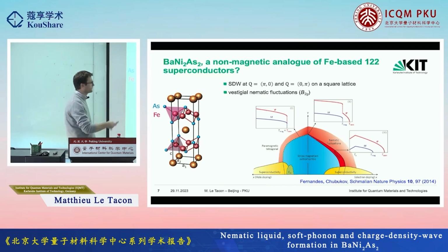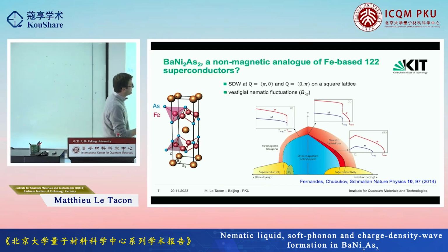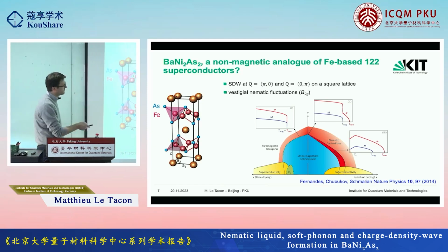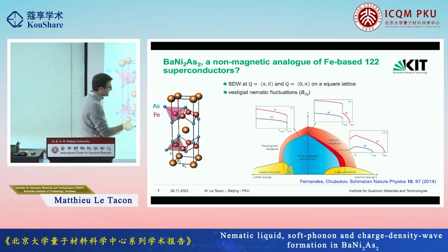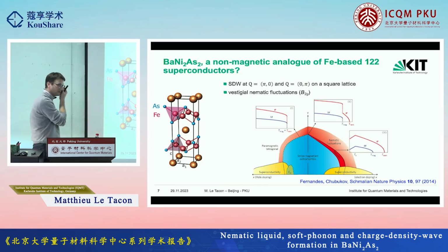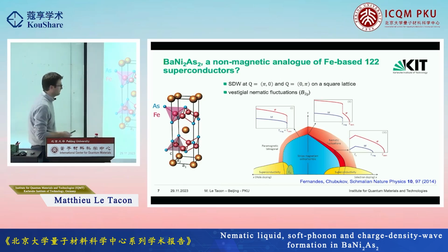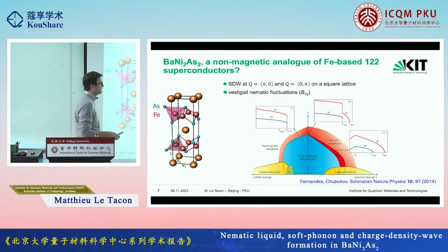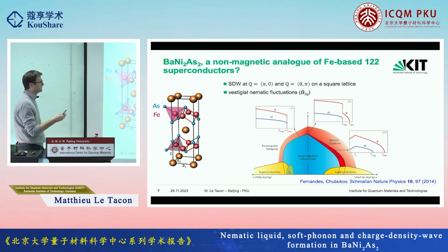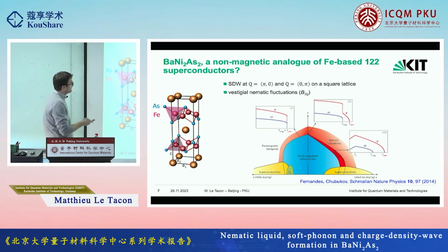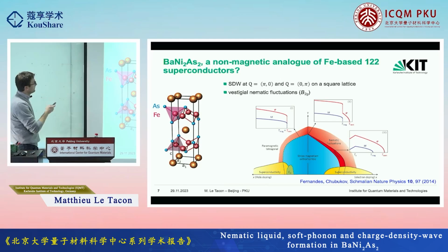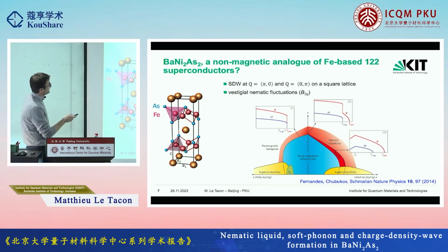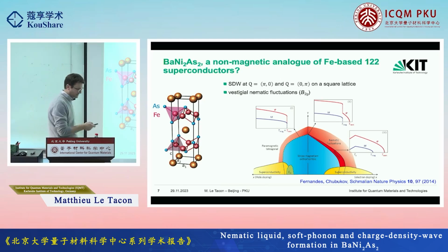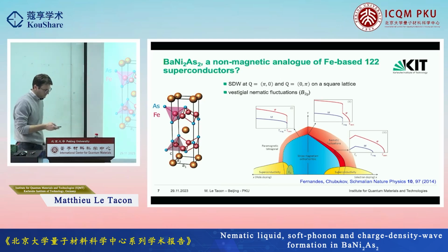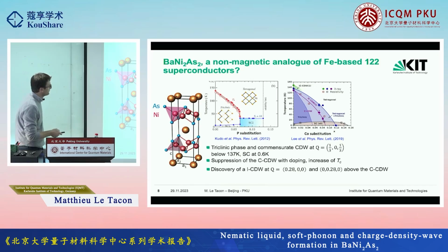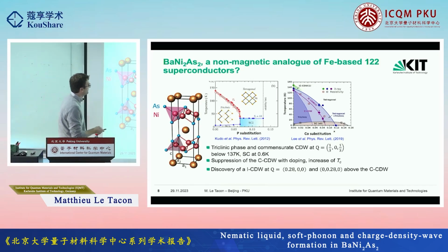It gives rise to a domain structure at low temperature, but those fluctuations themselves have been widely discussed, in particular in relation to superconductivity, and whether those nematic fluctuations could be mediating superconductivity, for instance, and more generally, the question of how they interact with superconductivity. Now the nickel compound is essentially a charge analog of the iron one, so it has no magnetic order, and it has a bit of a different phase diagram, which back in 2012 was studied, for instance, by Kudo et al.